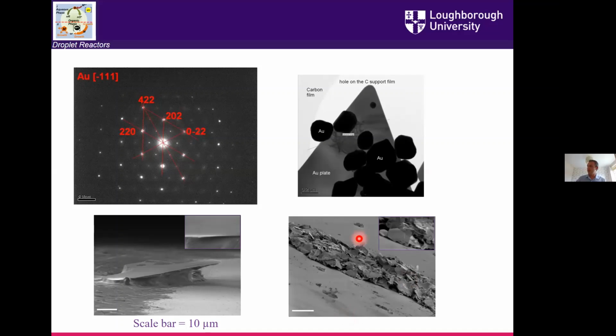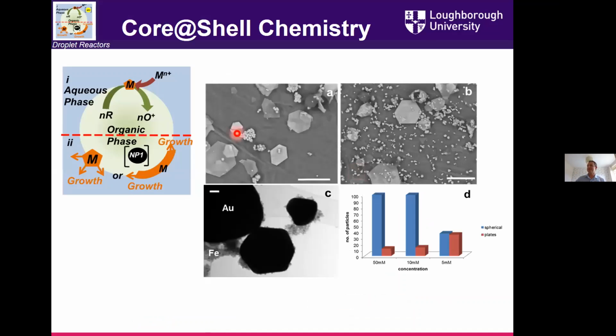And you can really make quite a lot of these. And one of the projects we had going on just before we were shut out of the lab with the lockdown was to start putting these onto electrode surfaces and to see if we could see any other different types of chemistry on those, which we haven't got through to yet. But you can make quite a reasonable amount of these in doing it. But it wasn't what I initially set out to do. What I wanted to try to do was to make a magnetic inner phase and a gold shell, inspired by some of the work using gold shells for imaging and analysis.